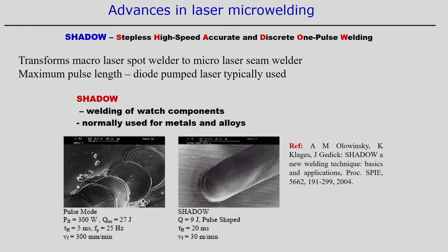Looking at how it works: the first mode is pulse welding, but in this case it is spot welding with overlapping spots, and the surface appearance is not good. The pulse energy is around 27 joules, peak power around 300 watts, with a velocity of 300 millimeters per minute. In that condition, simply overlapping pulses are joining the material, but the appearance is very poor.